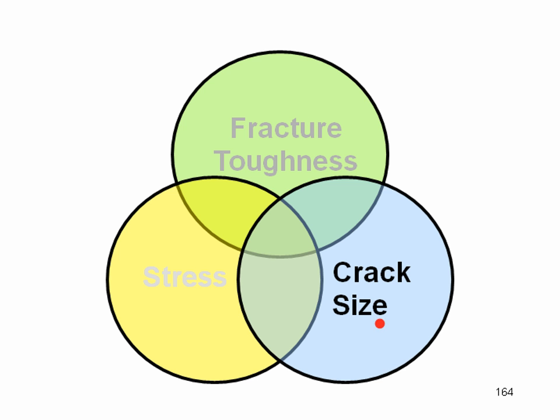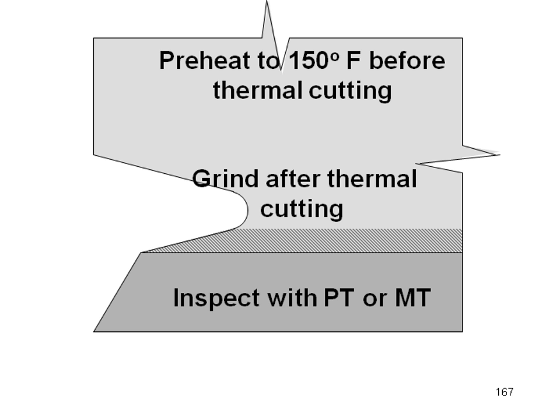Now here's one of the weld access holes from Orlando, and you see some notches and some gouges in this region. When the access hole was checked with dye penetrant inspection, the pink is indicative that the dye is seeping out through the white developer, and so there are pre-existing defects in the weld access hole. That's why AISC now requires that we make the access holes differently. We preheat the steel to 150 degrees for thermal cutting. This is for the jumbo sections.